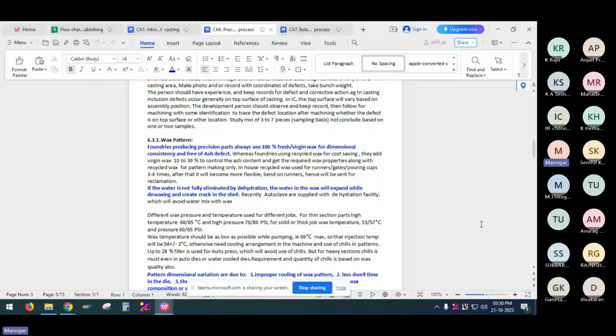And when we are de-waxing, the wax should be allowed to dehydrate completely. Otherwise, the water contained in the wax will expand and give gas problems in the castings, and cracks in the shell also.